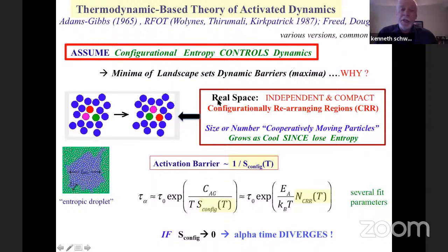Now, if we go back to Adams and Gibbs, there was a simple real space picture that there's some compact region of a finite number of particles. Those regions are independent in the liquid, and rearrangement in that region, called a configurationally rearranging region, is what the event is that we call the alpha process. And then you can think about either their size is growing as you cool, or the number of units that are moving cooperatively grows as they cool. And the reason is argued to be because you're losing configurational entropy.